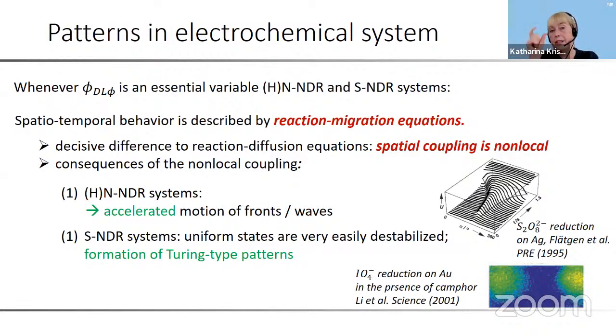dictates, on the one hand, the spatial extension of the pattern, or makes at least typical electrochemical waves of the type of HN-NDR systems or N-NDR systems much larger, also in S-NDR systems, by the way, than in chemical systems. So when you think of the spiral wave, I showed you the wavelengths of the arms were about 20 micrometers, this range. Typically in electrochemical systems, you have a millimeter, or at least 100 micrometer, millimeter, or even larger. And this is due to a very effective coupling, non-local coupling through the electrode potential. And this effective coupling in many situations also leads to stabilization of the uniform electrode surface and to a synchronization